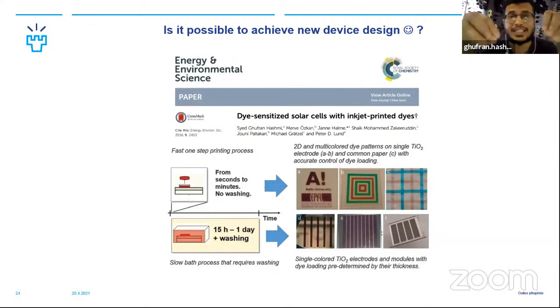And nowadays, since we all know that achieving higher short circuit current densities is possible by co-sensitization, and now even some controlled volume of both dyes have been mixed, if you see the recent reports. But previously it was very random: the dipping time in the both dye solution in order to achieve the co-sensitization was random. So that's why the mass loading for each individual dye was not possible to know.